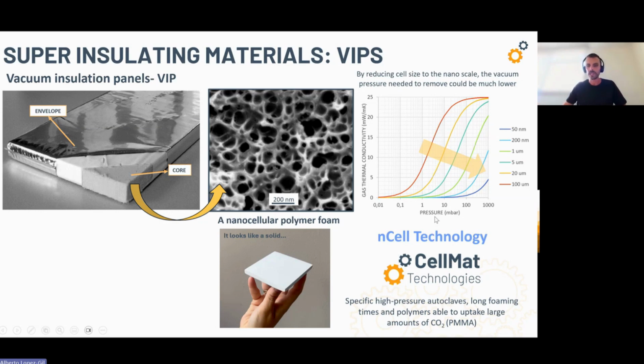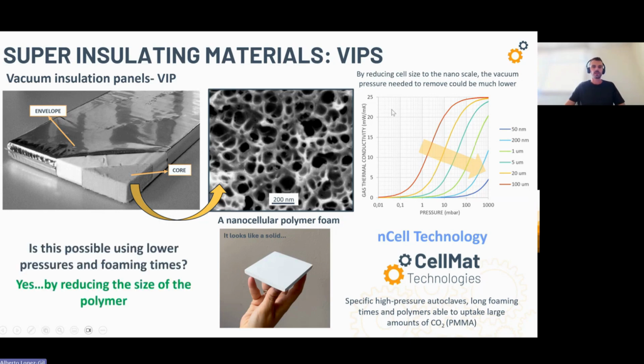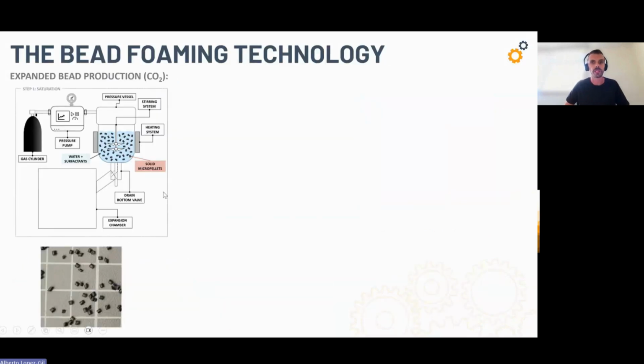The thing is that we need very specific technology. We need supercritical foaming using very high pressure, long foaming times, and polymers specifically developed to uptake large amounts of carbon dioxide, such as PMMA. So the question is, is this possible? Can we produce this nanocellular foam with open cellular structure by using low pressures and foaming times, not the pressure sometimes we need to produce this foam, sorry. Yes, this is possible by reducing the size of the initial polymer we want to foam. And this is possible by using the bead foaming technology.